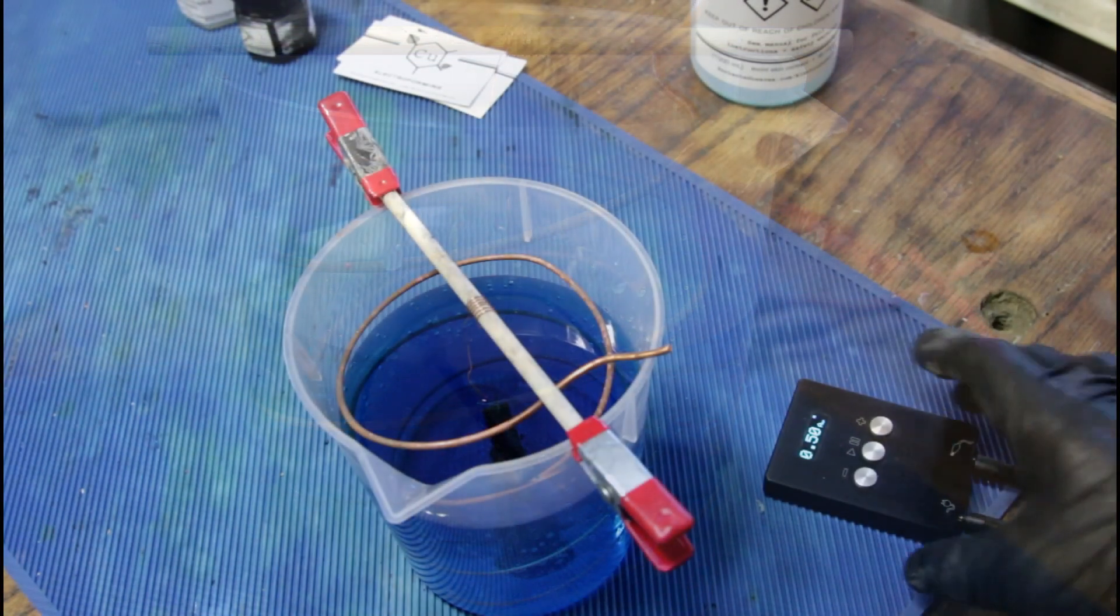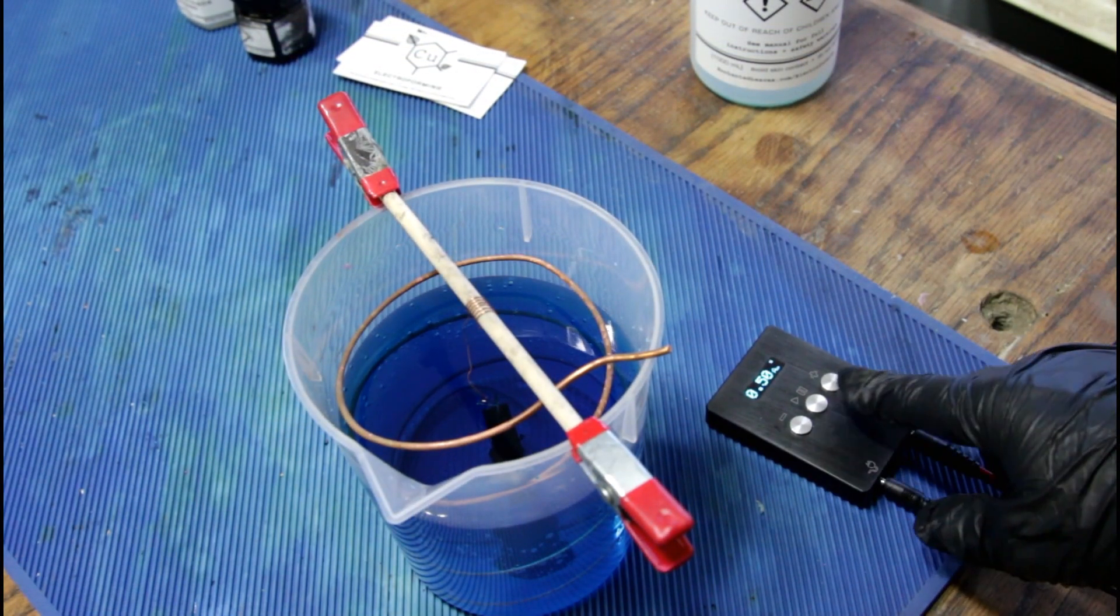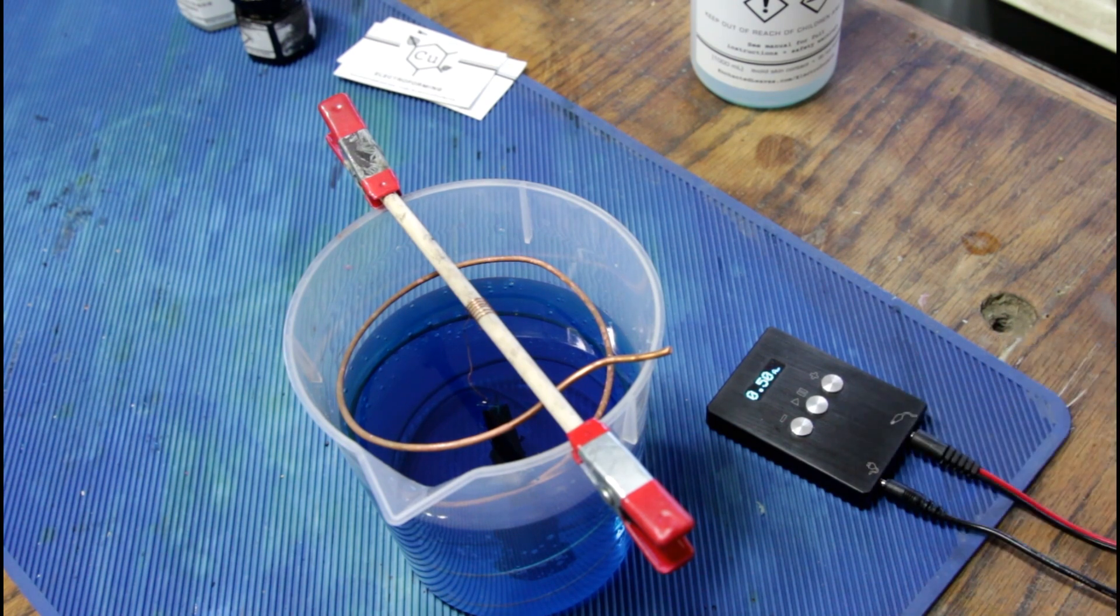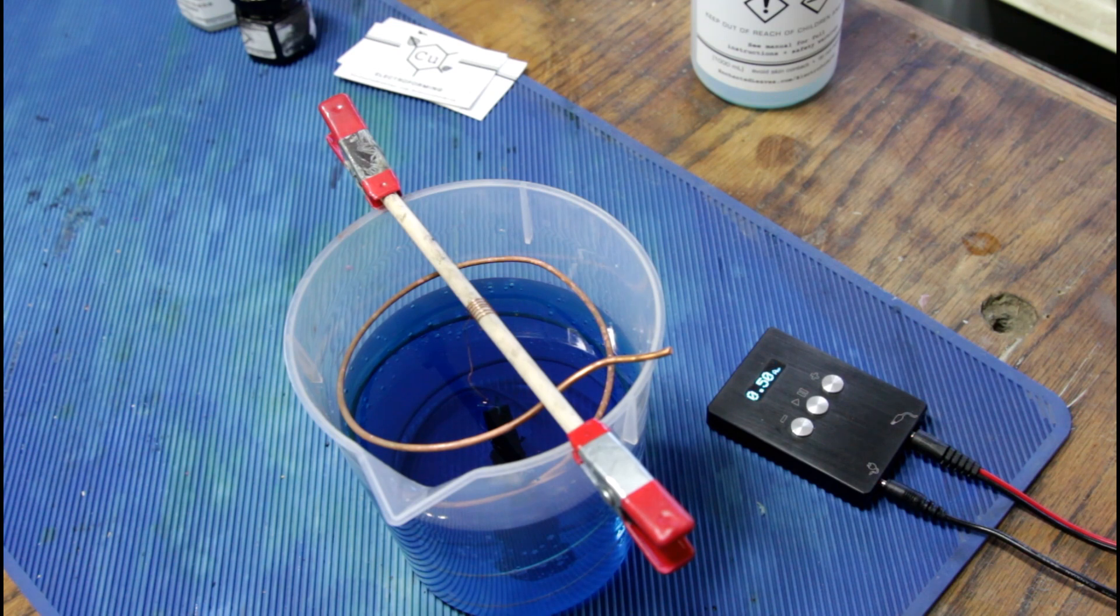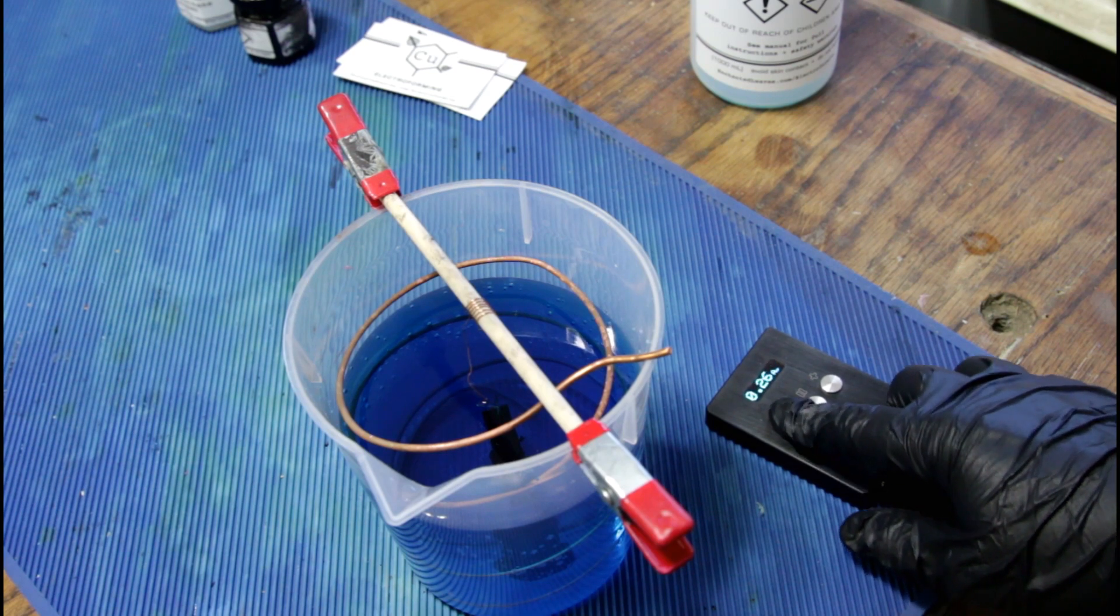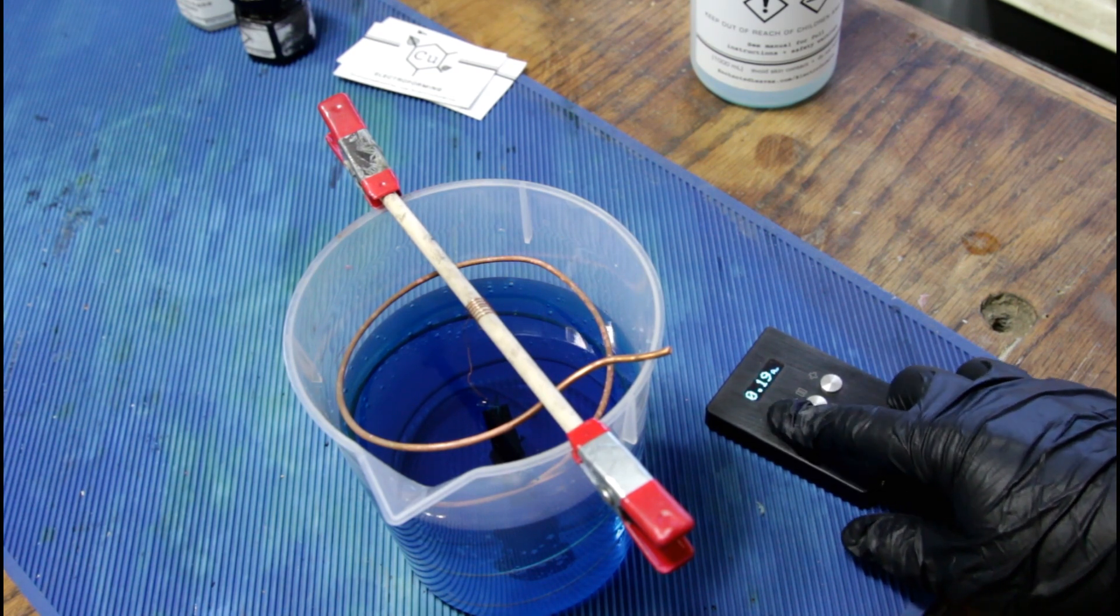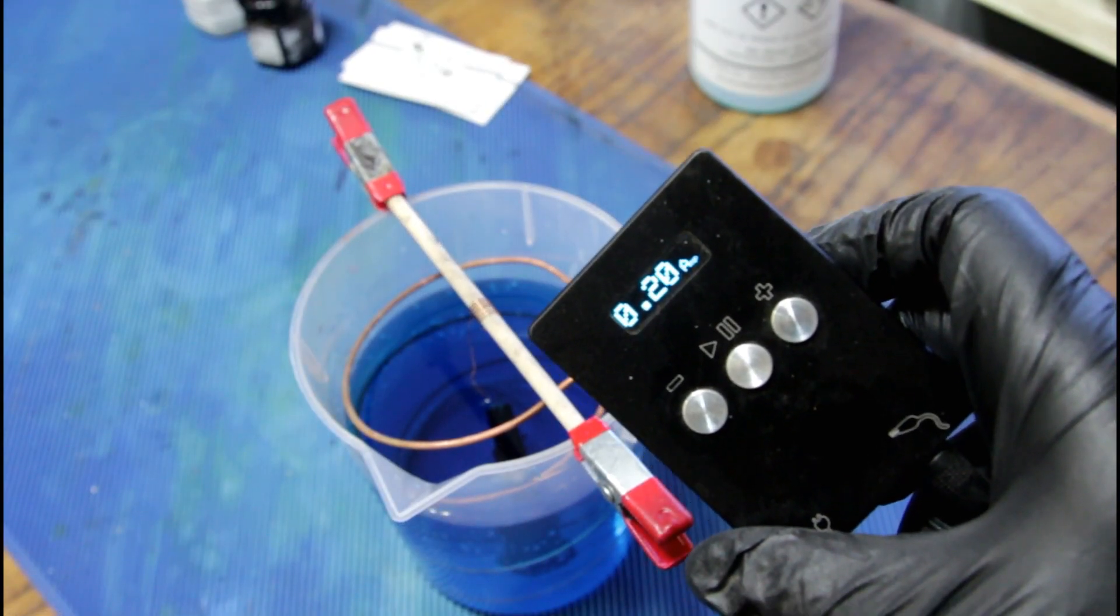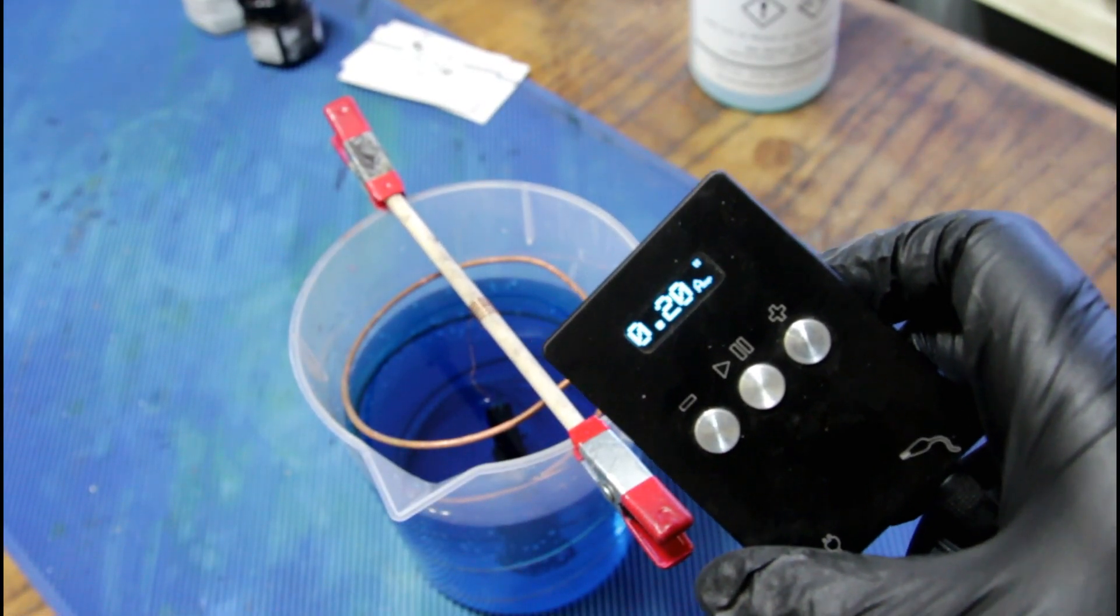Okay, so the kit that I bought actually came with a power supply, and this supplies one amp or less. I was reading all these different formulas on calculating surface volume and everything else. For me, I have found that a lower amperage, even if it takes longer, gives you more detail in a piece. I've basically been going with 0.20 amps.